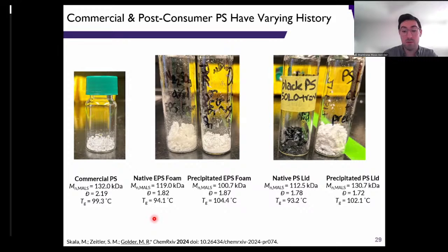And that, again, we surmise is due to the fact that we are removing at least some amount of the additives and plasticizers. These are all post-consumer proprietary blends, so we don't actually know what we're working with here. This is a little bit of a black box, but we know at least from the fact that we see a change in glass transition temperature that we're removing some amount of those additives. You can see here, at least with the black coffee cup lid, going from a black material to a colorless material is also good evidence.